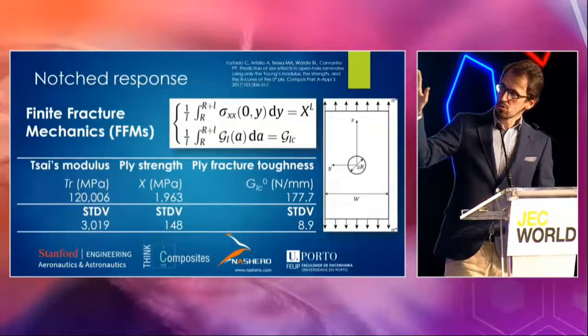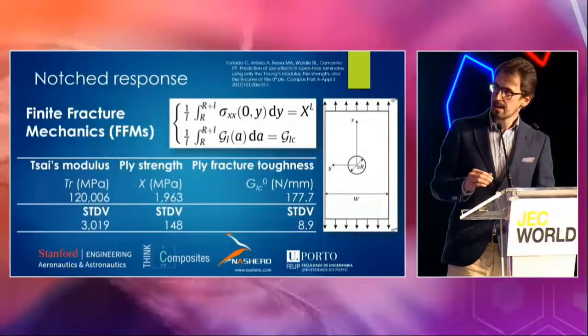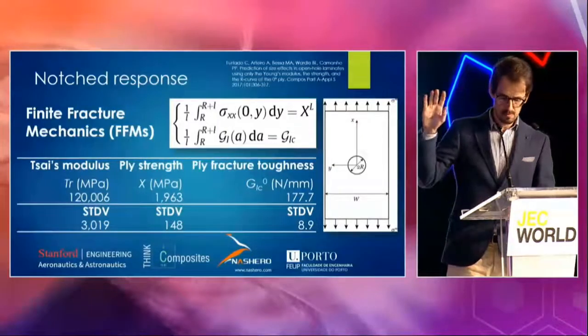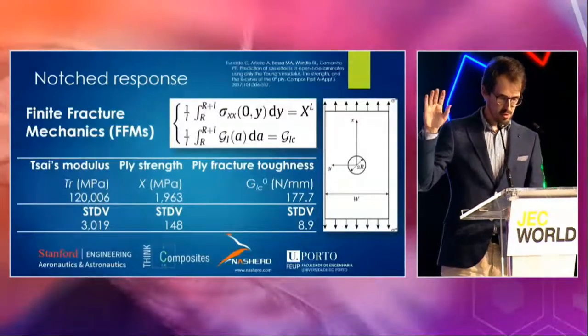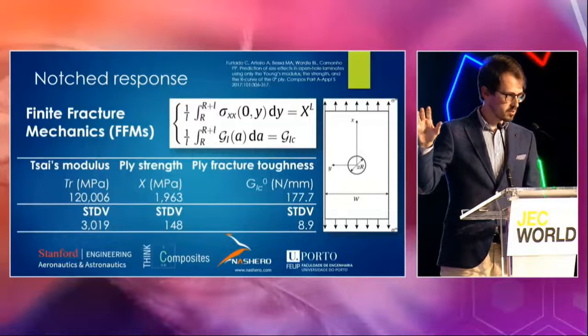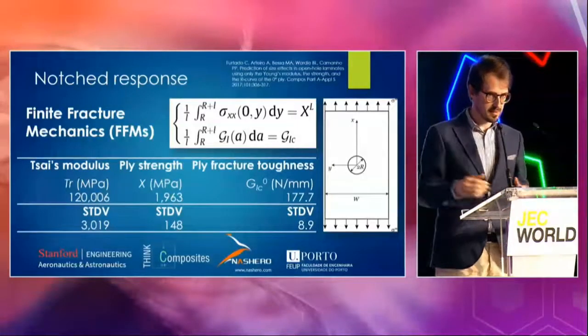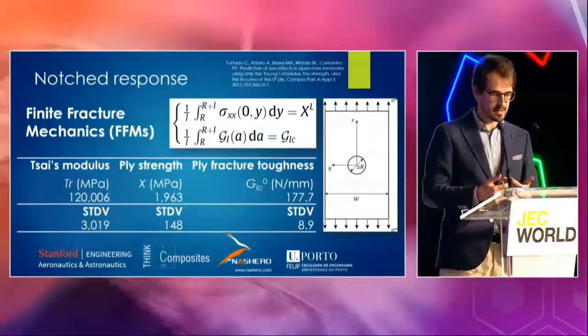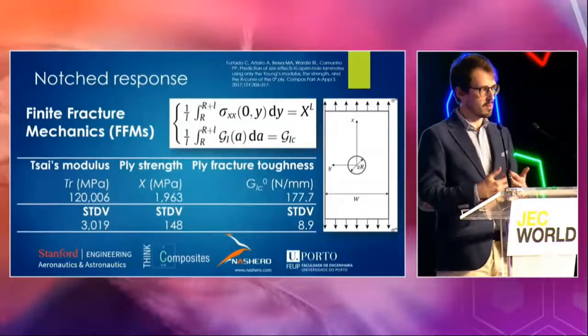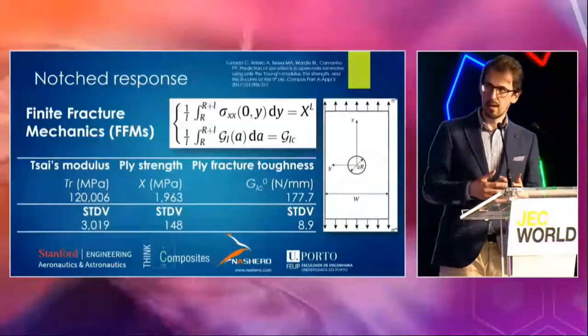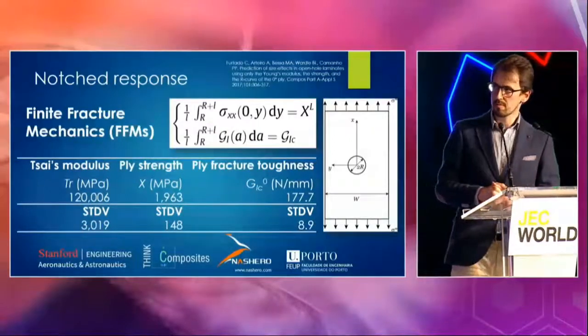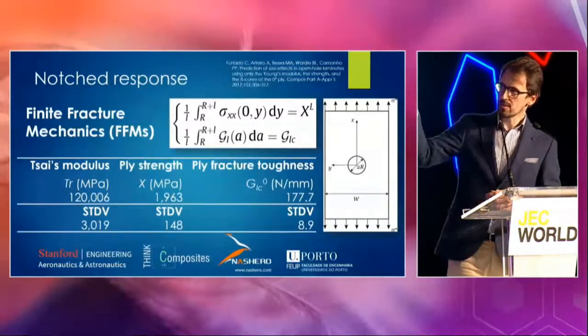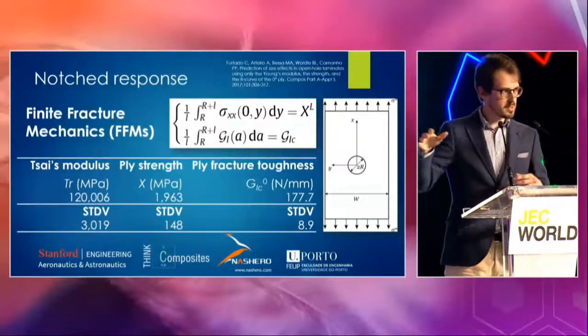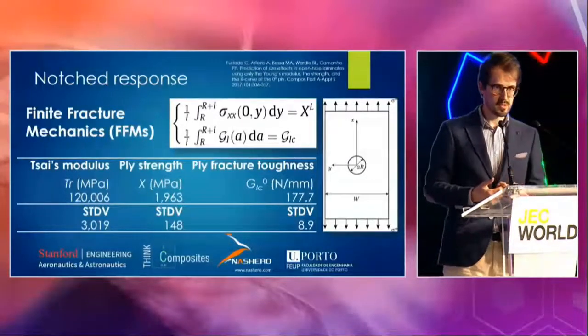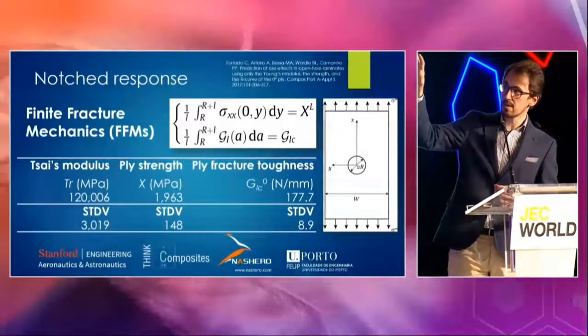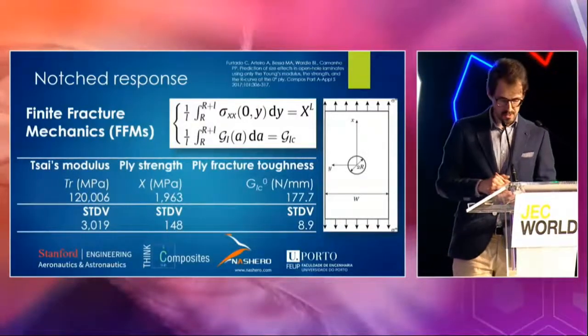So to solve the left-hand side of both equations, you just need the stress distributions around the hole and the stress intensity factor distributions for different crack length. These are things that you can get either from analytical solutions or from calibration in a finite element model if the laminate is too orthotropic. And on the right, what you have are the material properties, so the required ingredients to solve the system of equations. Okay, so you have the laminate strength in the top, and you have the laminate fracture toughness in the bottom.